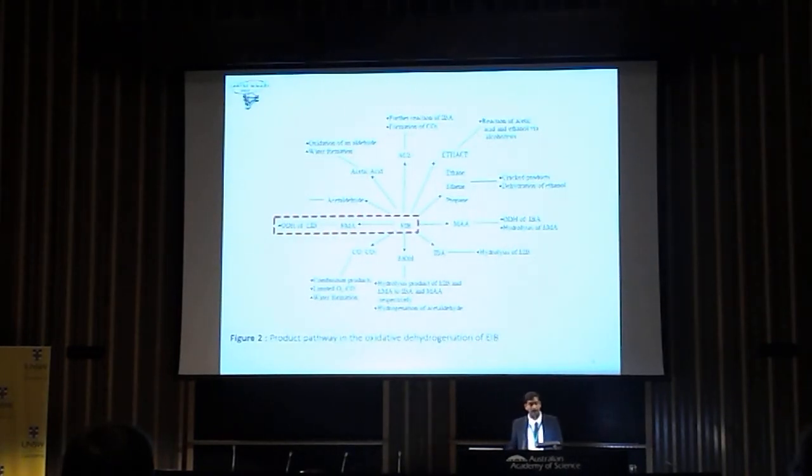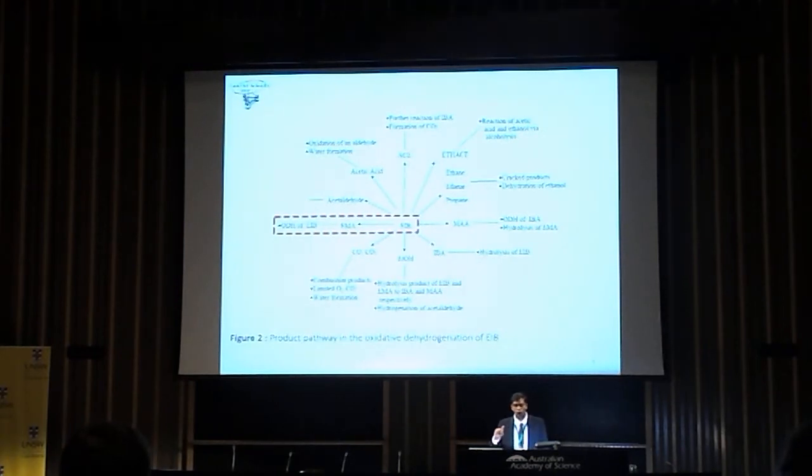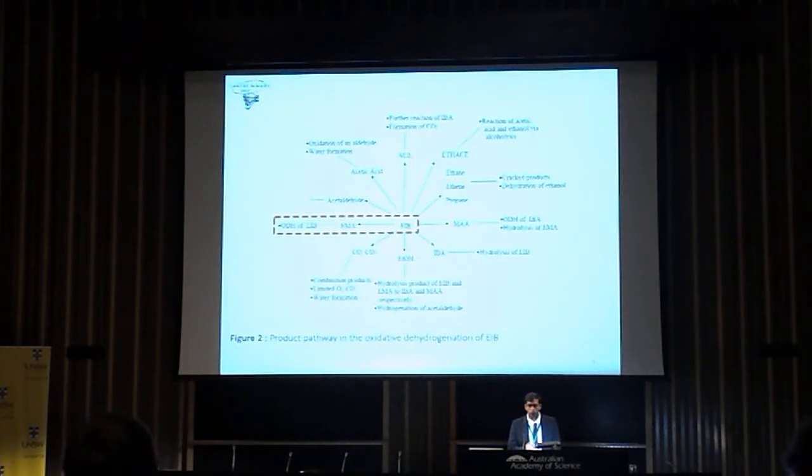The main influence of these side reactions is the phase transformation of our catalyst happening inside the reactor. So if we have to control all these reactions and go towards our target product, we need to control the phase transformation of the iron in the iron phosphate catalyst.